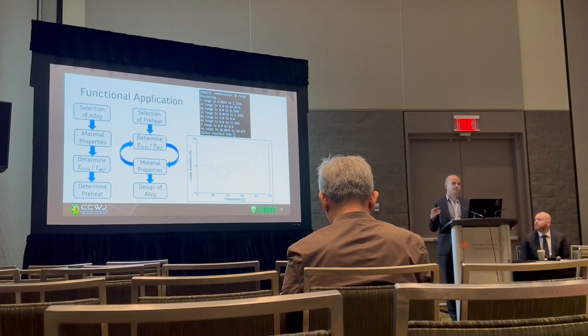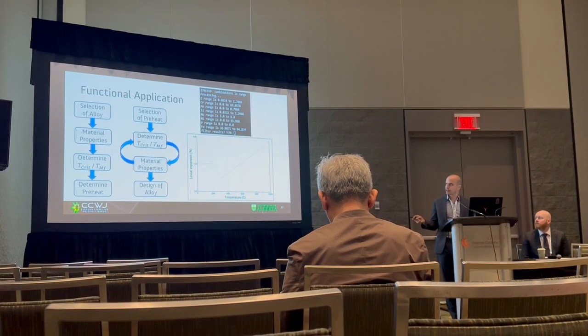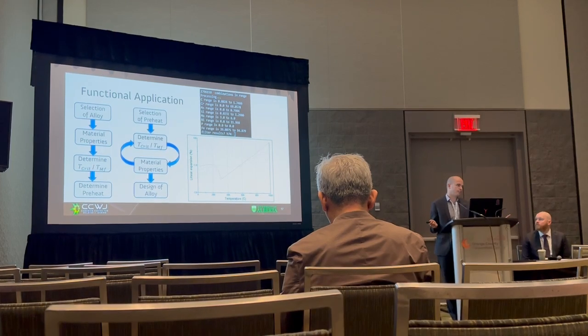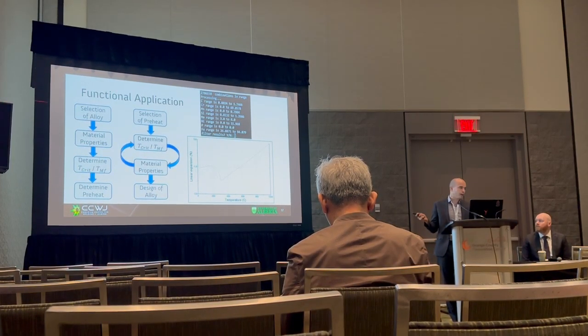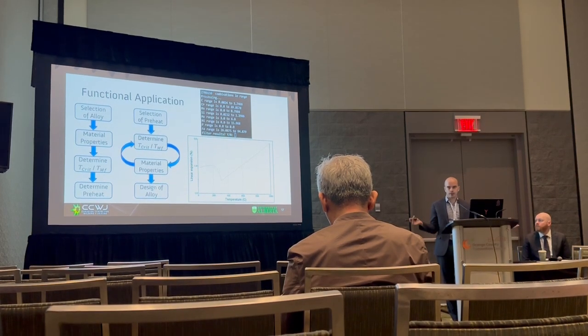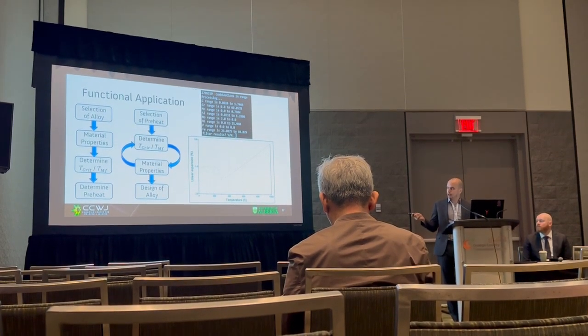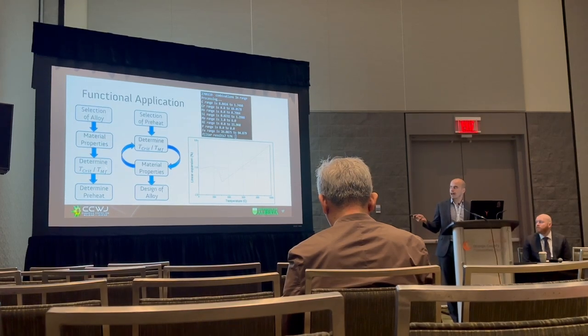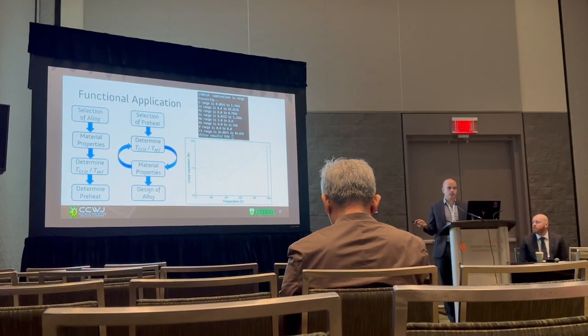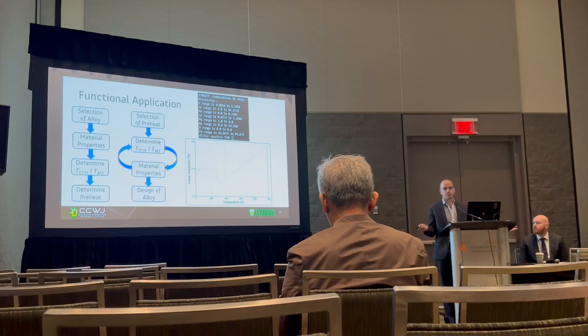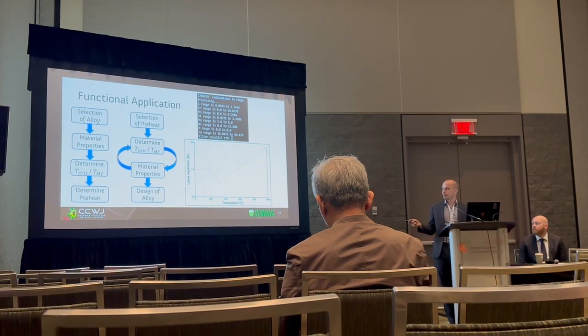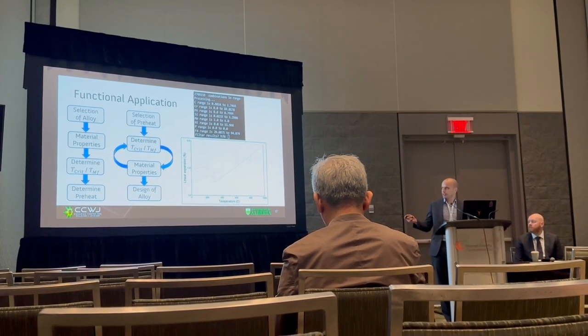And then just to help explain how this can be used by weld designers and welding engineers, you can do it in the reverse direction much more easily. If you know what alloy you're welding, regardless of the alloy, it doesn't even necessarily have to be classified as LTT, this would work for anything that undergoes a phase transformation. Then you know the material properties of it. It's easy to determine that TMF and T crit, and then you know exactly what preheat would get you the optimal residual stress. And of course, if you think back to that plot I showed you, the answer to this is actually quite simple.